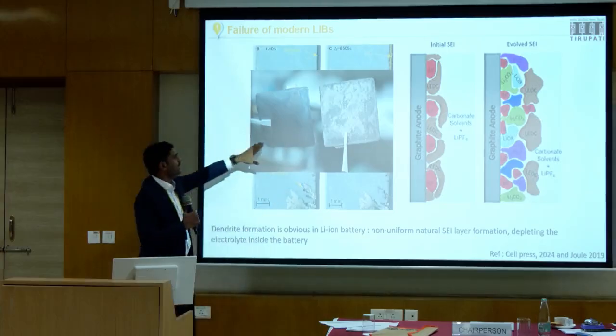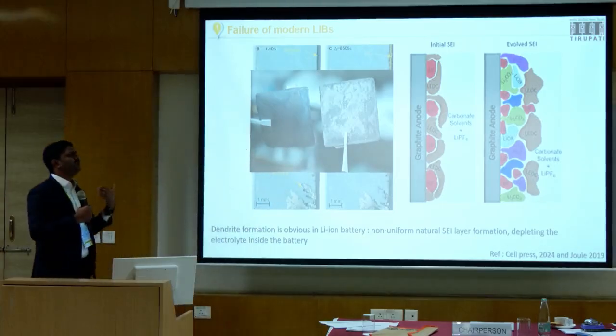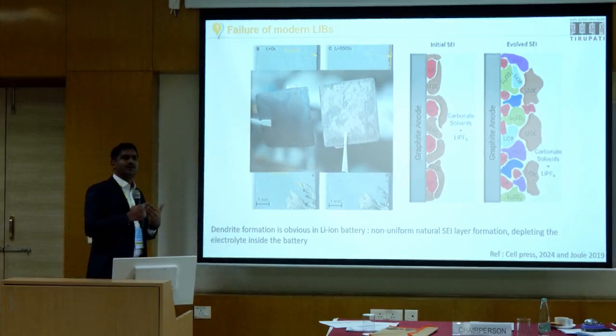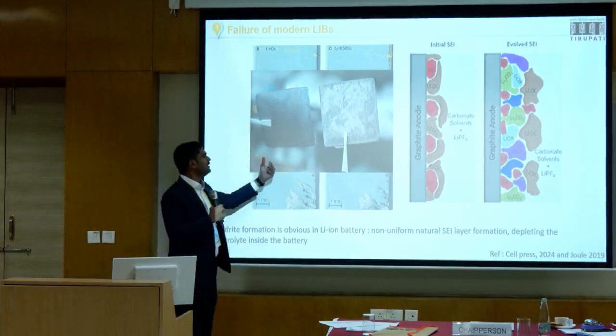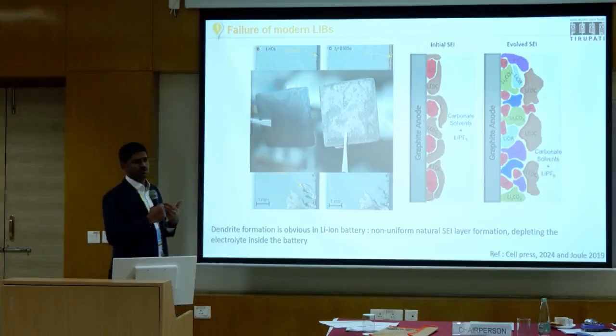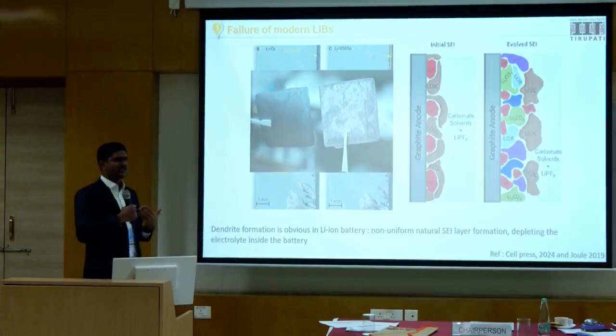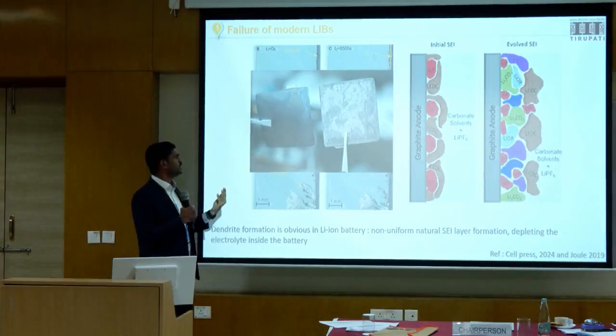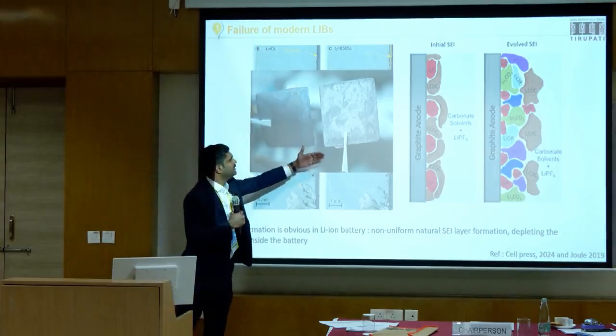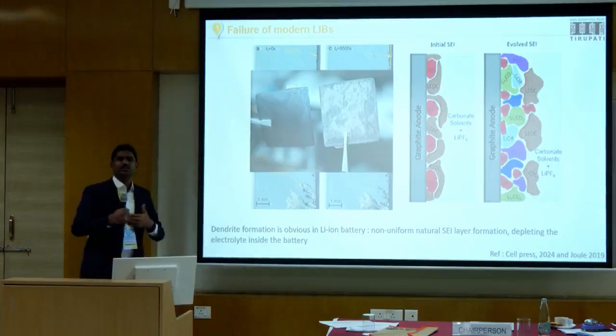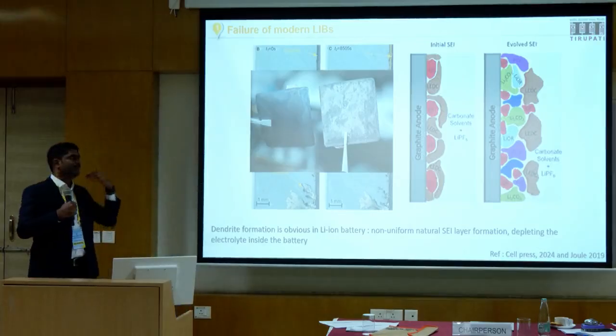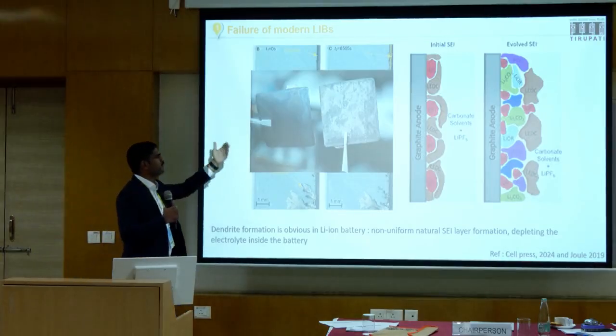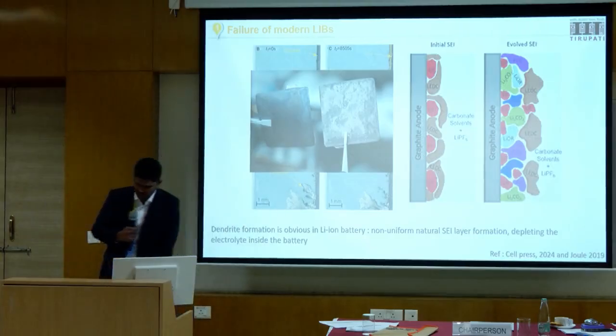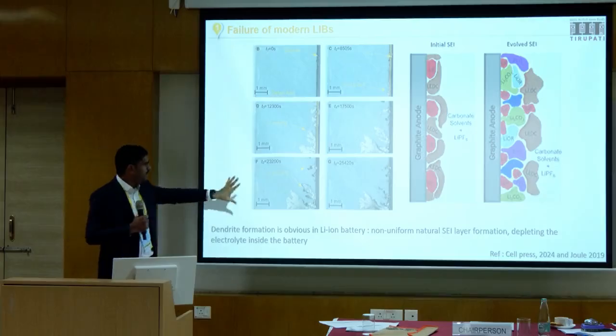So this is an inside view of lithium ion batteries after a few hundred cycles. What you observe here is that the lithium is supposed to move as an ion between the anode and cathode, but it really does not go that way. The lithium ions get converted into lithium metal and deposited over one of your electrodes, thereby making an internal short circuit inside your battery.